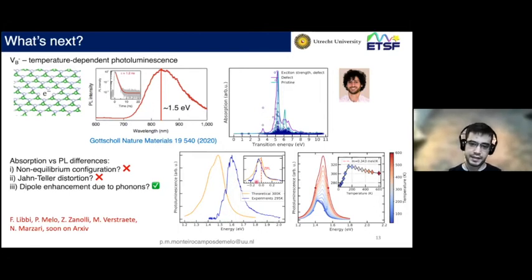And when we aligned the zero phonon line energies of both the experimental measurement and our calculations, we see that they match quite well. And it can be proposed that, if we track the full width at half maximum of the line as a function of temperature, we can actually propose the system as a good thermometer as a potential application.